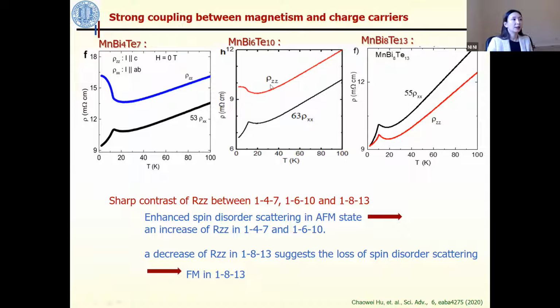However, if you look at the ZZ, which is when your current is along the C direction, for 147 and 1610, you can see your resistivity actually increases in the ordered state. That just suggests the reduction of the loss. Actually, it just means the increase of the spin disorder scattering. Again, it's consistent with the fact that along the C direction, the spins are actually antiferromagnetically